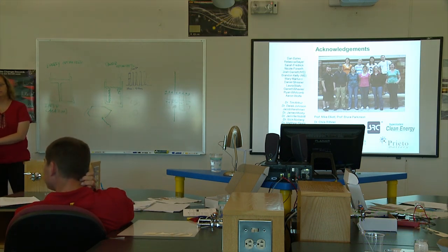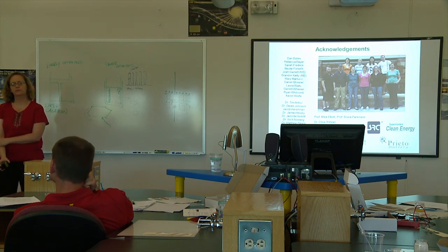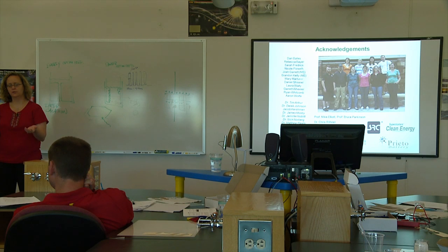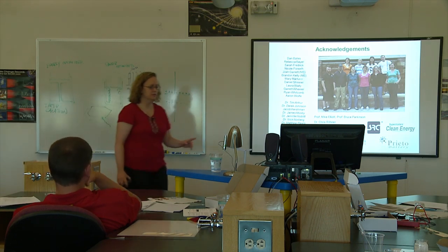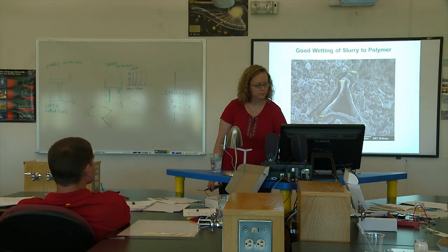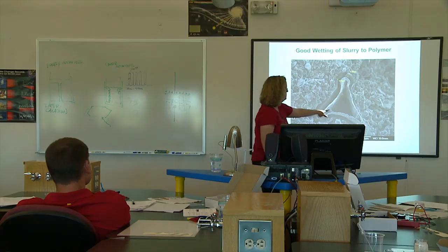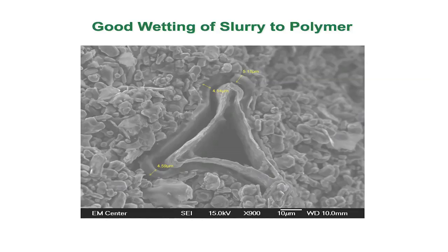So we buy it from a company. Originally, we were buying it from a company from the Netherlands. Now we're actually buying it from a company in China. And the way they make it is first they pressure extrude a molten polymer that when it cools, it gets all these air pockets in it. Then they use a chemical process to coat that with copper, and then they burn off all the polymer, and you're left with the foam. That's why if you look at this picture, the foam is hollow. This is where the original polymer scaffold was.